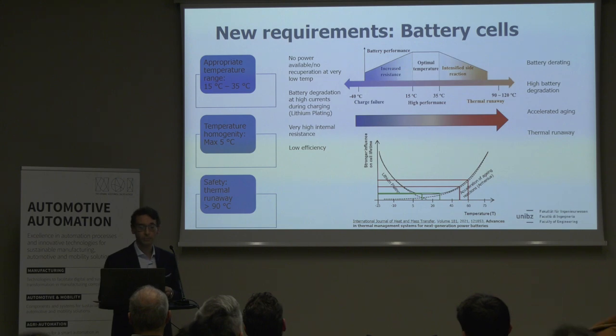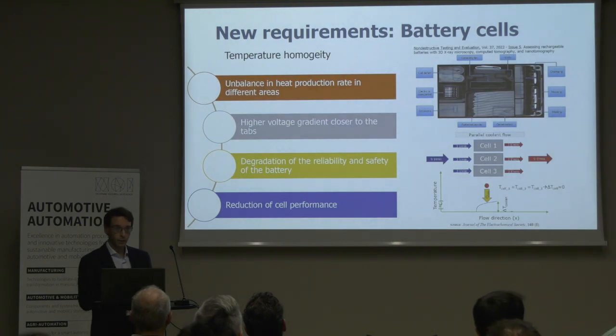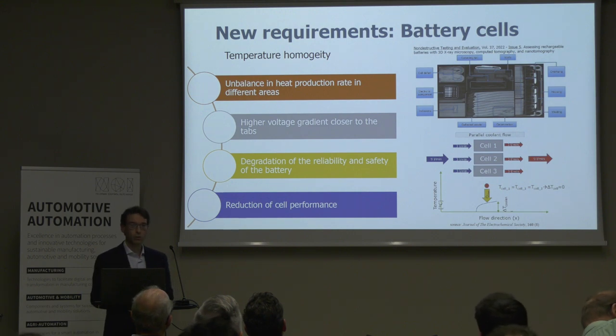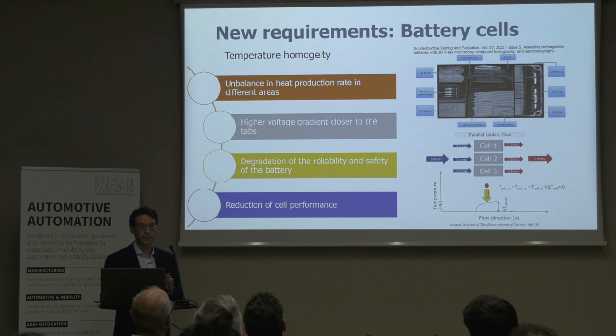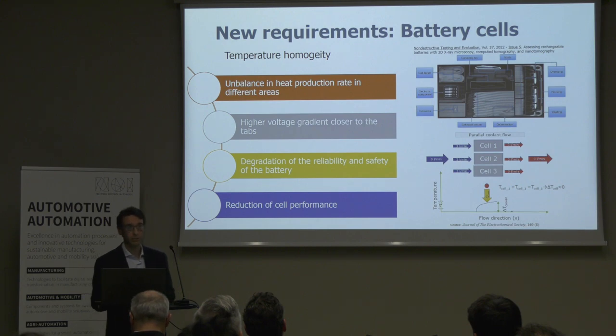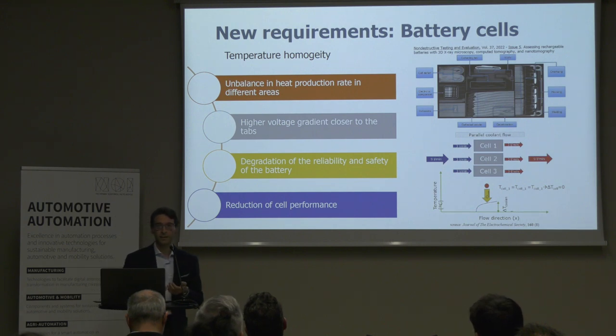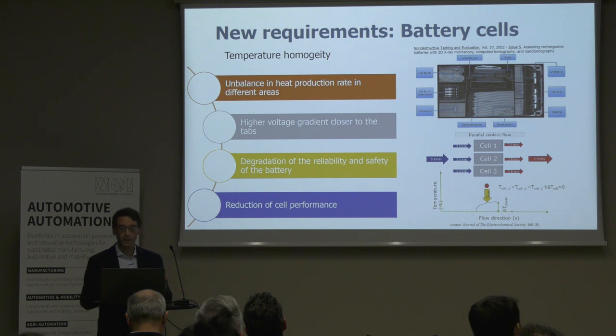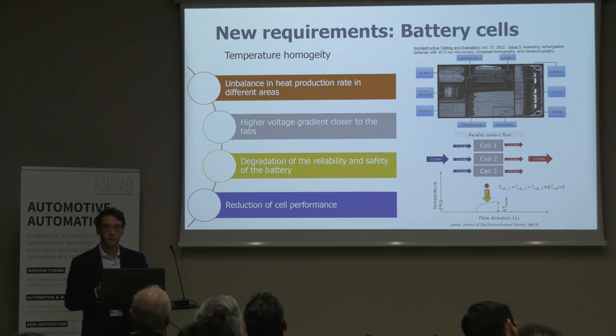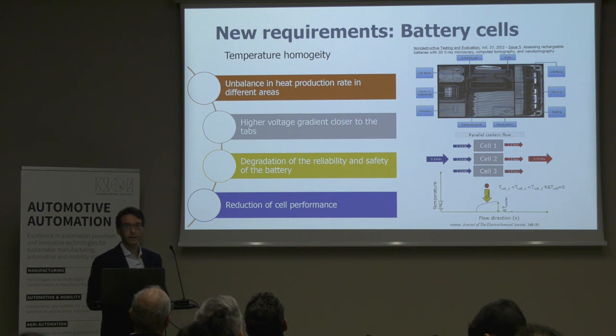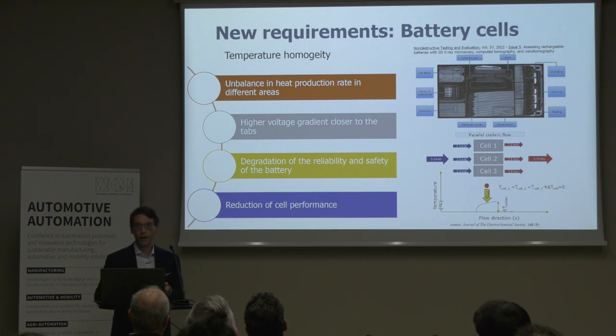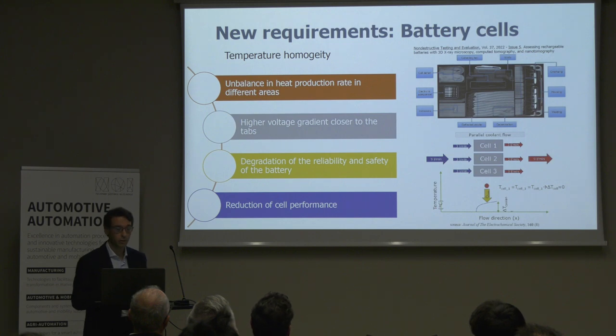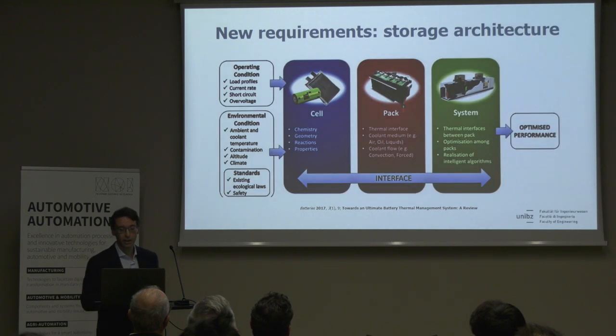So, thermal runaway. Another critical aspect is not only to keep the temperature in that range, but also to keep it with very good homogeneity. All the cells of the pack should be within a maximum of 5 degrees of temperature difference. This is very challenging because the battery itself, for its construction characteristics, is not homogeneous inside. As you know, there are many layers, and there are preferred paths for the heat. And of course, given the characteristics of the cooling or heating system that we have for the cells, it is impossible to guarantee exactly the same thermal management for every cell. So this requirement is also extremely challenging.